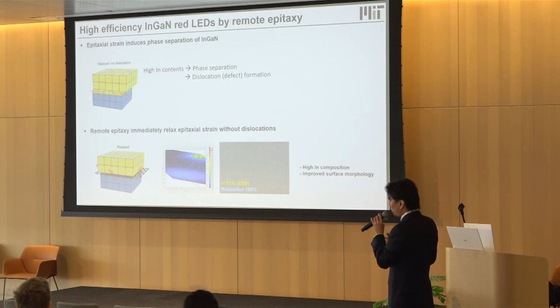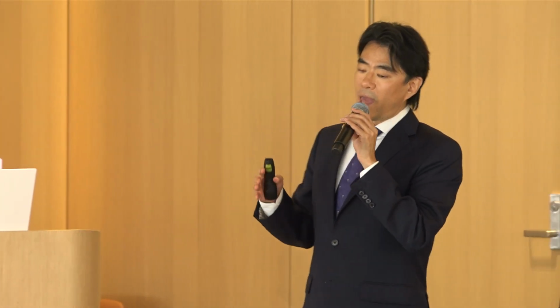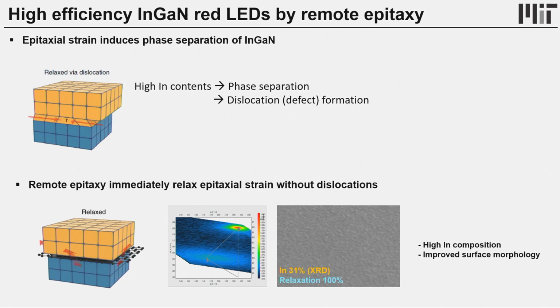At the same time, remote epitaxy will be able to relax the epitaxial strain immediately, not like the conventional epitaxy. In conventional epitaxy, we all know that it's very, very hard to make red LEDs out of the gallium nitride materials because you need to have a lot of indium in indium gallium nitride, but it's very challenging for two different reasons. If you have high indium contents, then there will be phase separation. So you cannot add indium to reduce the band gap to match the red. At the same time, if you add indium, lattice mismatch increases, then dislocation is formed.